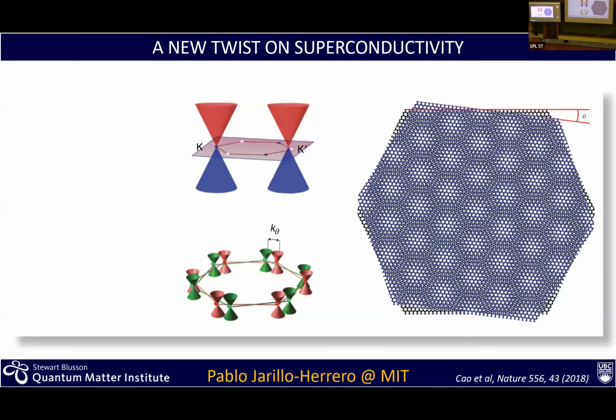This material is graphene. Graphene is known for this hexagonal type symmetry with Dirac cones, so these linear dispersive bands, energy versus momentum for the electrons, touching each other at the Dirac point with the chemical potential located exactly there. But now as you take 2 of these layers and put them on top of each other, the Dirac cones would overlap, but as you start twisting, they move away from each other, as in this case. And now if you allow these layers to interact, if there is a finite interaction between the layers, this is going to lead to a reorganization of electronic structure.